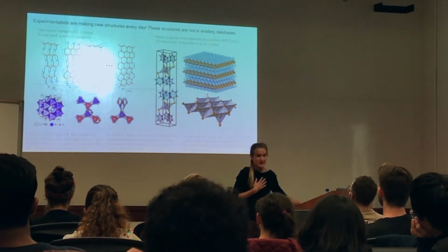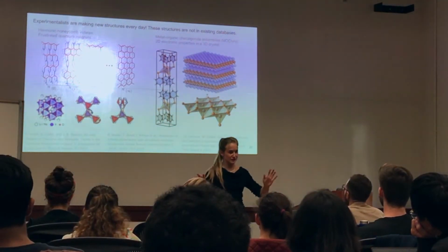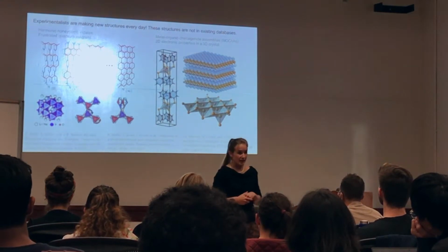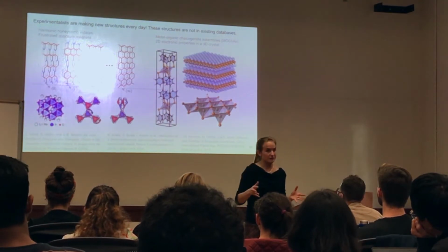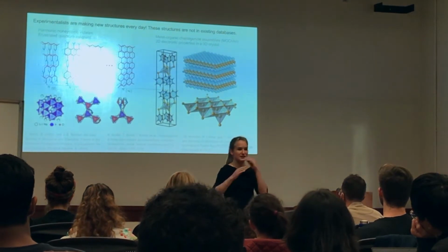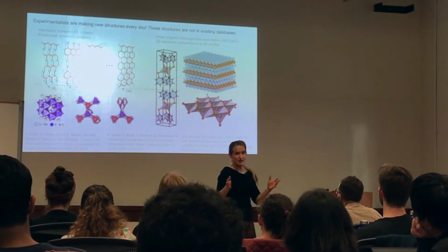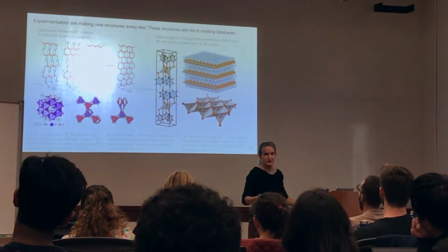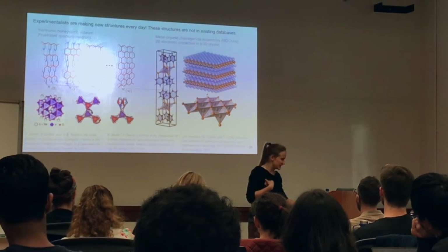So these are two examples from my PhD research. These are harmonic honeycomb iridates, which have exotic frustrated quantum magnetism at low temperatures. And then there's these metal organic chalcogenide assemblies, which are self-assembled, meaning pretty easy to make, bulk materials. So they're three-dimensional, but they have low-dimensional properties. So super interesting. You don't have to exfoliate it to one layer for it to have quantum confinement behavior. You just get it from how the crystal is structured. So these are really cool. I would love to be screening for materials like this in my pipeline instead of waiting for experimentalists to be able to characterize them.